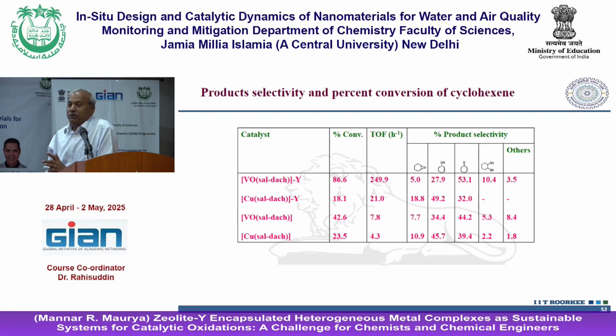But later we have done it, but we observed that if the reaction is carried out under basic condition, because acidity of the zeolite is the major factor to control such a reaction in terms of the product. When you make it slightly basic, you can control the formation of epoxide and you can increase the conversion of epoxide. Sometimes when you change the ligand, that also works.